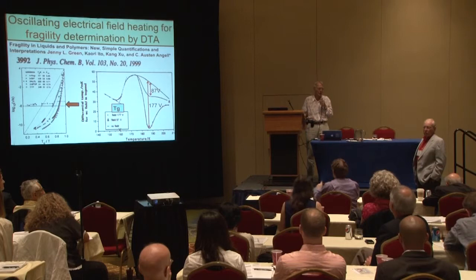Let me say a word on the viscosity business, because one of the most striking things of water itself is the behavior of the transport properties. Valeria mentioned power laws, which apply to the thermodynamics, but they're strikingly applicable also to the transport properties, diffusivity and viscosity, and spin-lattice relaxation time, which is one of the best ones to study because you can do it on these emulsion droplets. But again, as you raise the pressure towards 2 kilobars, or you raise the composition towards the edge of the glass-forming range, all those power laws disappear.